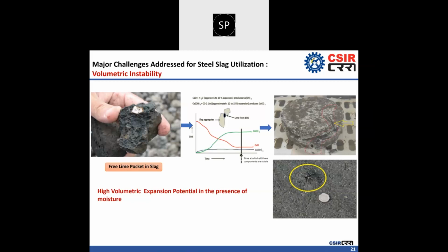With the help of this weathering and aging treatment, we can reduce the free lime content to less than 4%. And a reduction in free lime content will indirectly reduce the potential of volumetric expansion, and when the volumetric expansion is less than 3%, then this sort of material can be utilized for road application.